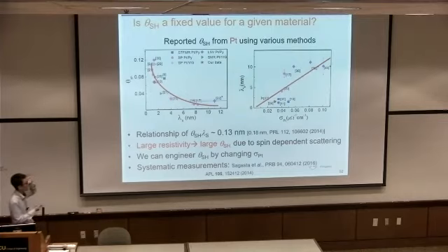So you inject charge current into your material, then we want to increase the scattering as much as possible. And you have a lot of different types of scattering, like Professor Lee introduced: skew, side jump, and so on. But once you have more scattering, what will happen? You also have a higher possibility of spin-dependent scattering. Then once you have more spin-dependent scattering, basically you can separate spin up and down in different directions. So that's why large resistivity will give us an effectively large spin Hall angle.